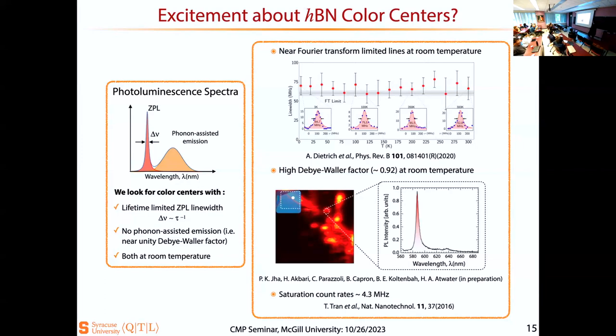Then in a typical, let's say, any other sample which you work with, very regularly, we get a very high Debye-Waller factor. And Debye-Waller factor is basically the ratio of how much of the intensity goes to the zero phonon line compared to the total emission itself. So if you really want to have a single photon source, what do you want to do with a single photon source? The first thing you want to harness is quantum interference. To be able to harness quantum interference, you want to have the photons be as identical as possible within the line.